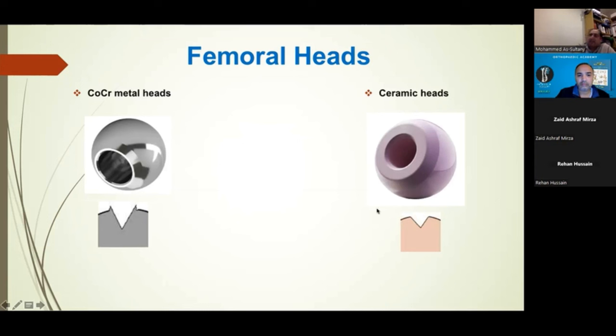The ceramic head itself has gone through three generations of change over time. There were problems with brittleness initially, fracturing, but over time the way it's made has been substantially improved, which has made it more durable. Still brittle, of course, as a ceramic material. And the main problem really is fracturing, particularly with acetabular liners. If they're not quite seated properly, or the acetabular component is malaligned, then you can create a lot of stress on a particular point, and that can make it prone to fracturing.